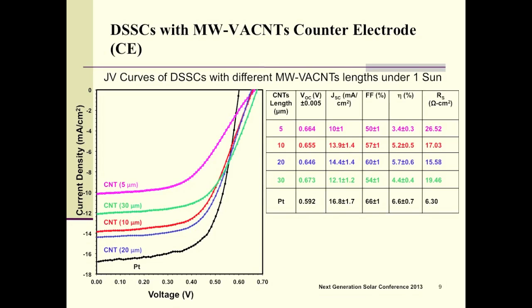And these are the JV curves, and the main parameters extracted from those dye-sensitized solar cells. You can see that the open circuit voltage for vertically aligned carbon nanotube based dye-sensitized solar cells is higher as compared to platinum, but the JSC is also increasing with increasing length up to 20 micron carbon nanotubes dye-sensitized solar cell, and then it decreased for 30 micron. The same trend we found in our fill factor and also our efficiency, and we got 5.7% efficiency for our 20 micron carbon nanotube length dye-sensitized solar cells.